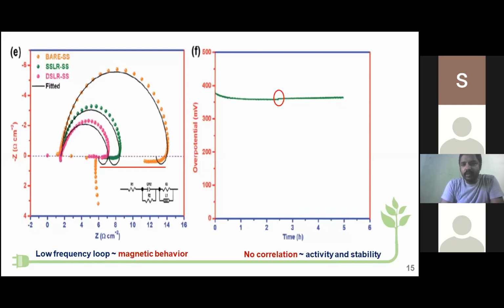And figure F is for the long-term stability test, that is chronopotentiometric curves, which are recorded at a constant current of about 10 milliampere, because that is the fuel cell output current. Here, initially the overpotential is decreasing up to 2.5 hours. After that, it starts to increase and attains a steady state.